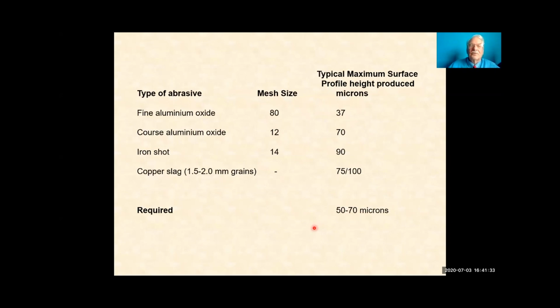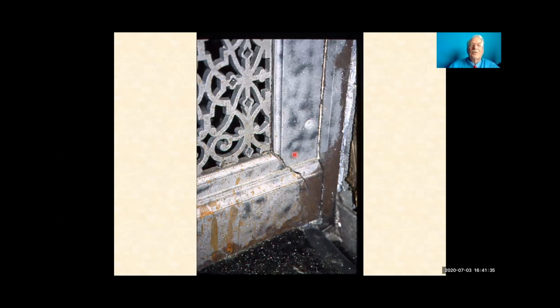And this is how not to do it. This is cast iron, and it has on it a black surface. It's called foundry skin, and it's a little bit of silica that burnt onto the surface when the cast iron was in the mold. And it sticks really well, and it acts as a very good protection. It keeps the moisture and the oxygen away quite well. Now, the paint manufacturers don't like it. They say they want 100% clean metal. We in the conservation industry say, well, it's actually better to leave this historic coating on.